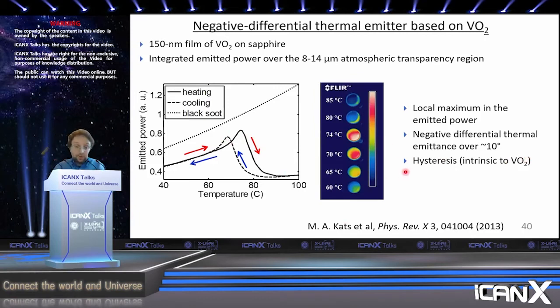So we took a commercial off the shelf mid-infrared camera and pointed it at the sample at different temperatures. And you can see that as you increase the temperature, the sample looks like it's getting hotter in the camera. And then you increase the temperature some more and it looks like the sample is getting colder, even though in reality it's getting hotter. And this is happening because of this negative differential effect. The reason we call it negative differential is because the derivative over here of this power versus temperature curve is negative. And so we thought this was very compelling, both conceptually and also for applications in thermoregulation and infrared privacy applications and so forth.